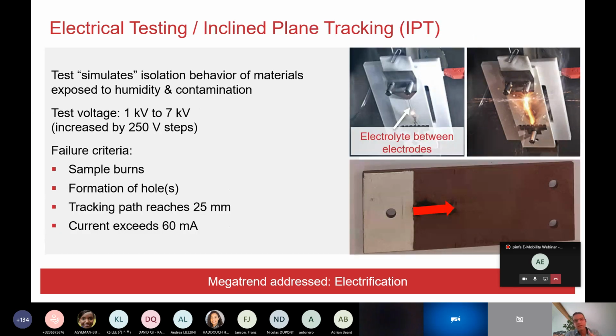The last test is the inclined plane tracking test, what you see here. This design already considers very high voltages, up to 7 kilovolts. You see that the electrode design is now different. The path between the electrodes is much bigger compared to CTI, but you have once again the principle that an electrolyte is flowing between the electrodes, and you analyze the material behavior in between. Of course, typical failure criteria like burning samples, formation of holes, tracking path length and the like are considered here. So for the time being we don't have the new adjusted CTI test.